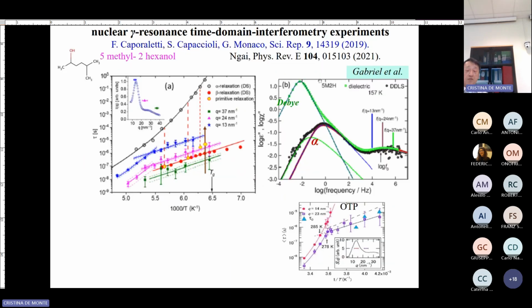So number one, this is a very elegant experiment, only recently done by the group in Trento, in collaboration with Simone. They use a very advanced method called TDI, time domain interferometry, and they are able to look at the dynamics in a very microscopic way. They see the alpha relaxation over here, and then they look at different Q, the so-called structure factor. At high Q, which is local, they found this relaxation, which is the Johari-Goldstein relaxation.